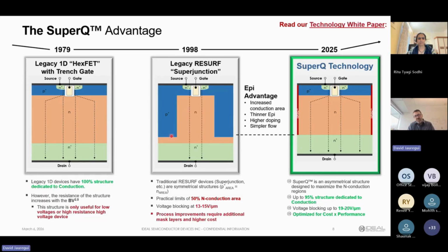And so now what this region looks like is what we call a silicon mesa. So it's got that shape of a mesa. And so really all the current now is only flowing through this region. And the reason is you need these P regions to charge compensate the drift. So every hole carrier in this P region has to equal the N, or the electron carrier, in the drift region. And so it's a combination of these two P pillars that allows this region to charge compensate.